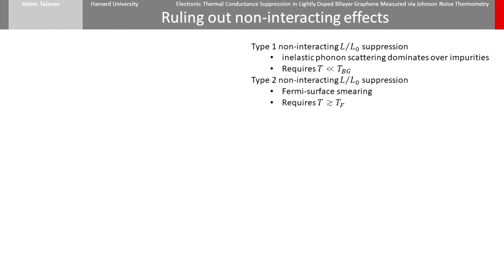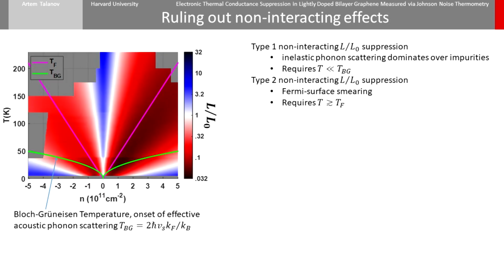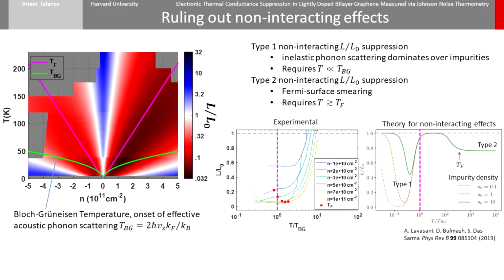There are some effects not caused by electron-electron collisions that can suppress the Lorentz ratio. The first type is caused by inelastic phonon scattering, and the second is caused by thermal smearing of the Fermi surface. The first type occurs only when the temperature is much less than the Bloch-Grüneisen temperature. In my data set here, I've indicated the Bloch-Grüneisen temperature for each density with the green curve. This is a plot showing theoretical calculations for the Lorentz ratio in a non-interacting system. Below the Bloch-Grüneisen temperature, there is a strong suppression of the Lorentz ratio. The degree of suppression depends on the relevance of impurity to inelastic phonon scattering.